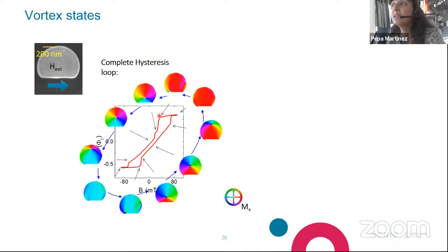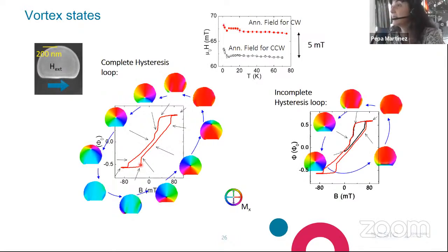You are able to nucleate a clockwise circulating vortex or a counterclockwise circulating vortex, depending on which field you are nucleating the vortex. Okay, if the field is positive, what corresponds here to the red color, that means the magnetization going to the right is along the applied field, you will nucleate a clockwise vortex, and the opposite will happen if your vortex is nucleated at negative fields. Okay, this tells us that we can choose the circulation of our vortex, but we can also prove that we are able of doing so, and verify that experimentally.